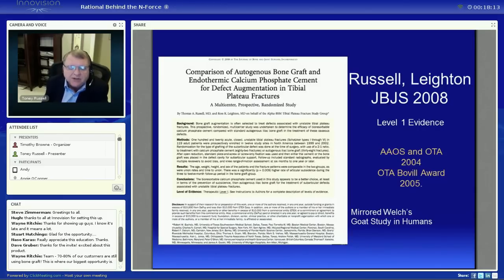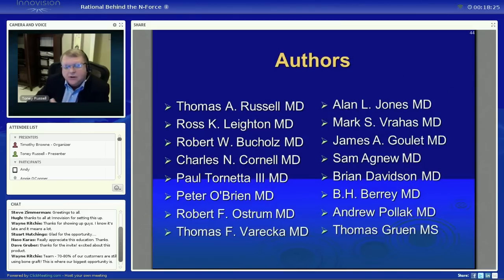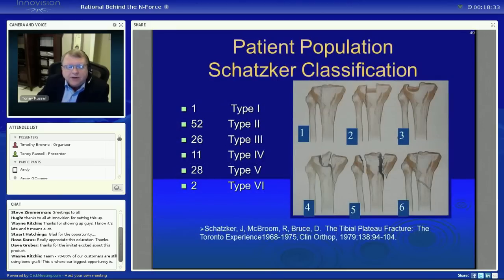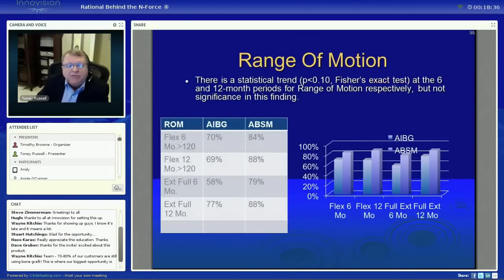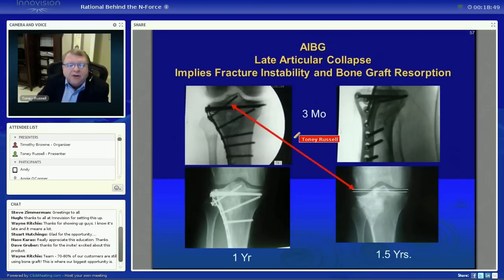Now, we did this study. This was published in JBJS 2008. It's the only level 1 evidence for any calcium phosphate cement that's really out there, comparing it to autologous bone graft. And we found the very same thing that we saw with the goats. We got a group of people that are all tops in their field. They're trauma surgeons. They know how to do this stuff. We did the tibial plateau model. What we found was there was a trend to better range of motion at 6 months and 12 months in the group with the cement augmentation, not the bone graft. So again, relating to the stability issue.